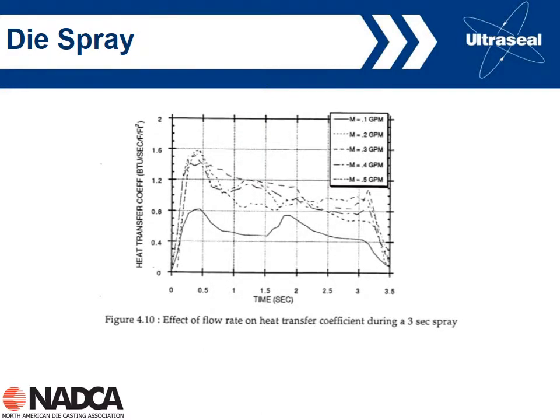And again, this is showing the data we talked about before, where we're looking at the heat transfer against time. At low flow rates from 0.1 to 0.2, yes, we can change it, but from 0.2 upwards to 0.5 basically has no effect on the heat transfer rate in the die.